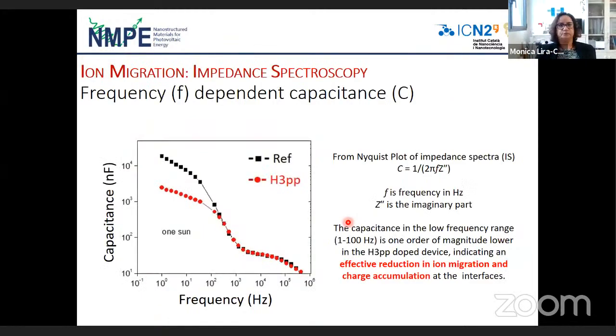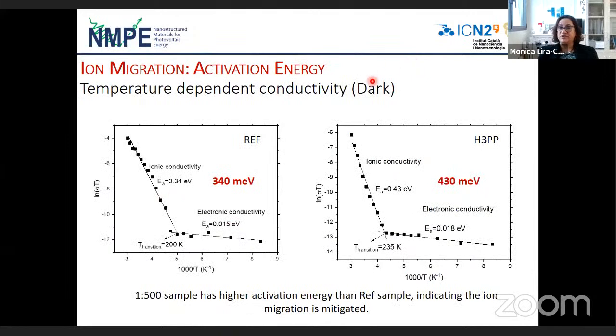One more thing that we did is try to see this relation, since we know that stability is related to ion migration. So we made some impedance spectroscopy to analyze if we have some reduction of this ion migration when we add the additive. We effectively observe that if we add this additive, we have this reduction in ion migration. However, impedance spectroscopy is not as good as certain other techniques, so what we did next to also see ion migration was use of activation energy. We analyzed our material with and without the additive by temperature dependent conductivity in the dark, and we very clearly observed that activation energy for our material was larger than the reference material without the additive, meaning that ion migration is mitigated.